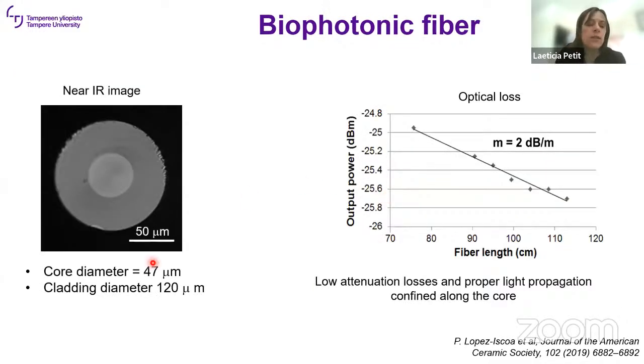So here's the near infrared image of the fiber. So the core diameter is 47 micron and the total diameter was 120 micron. And we got 2 dB per meter losses. So the low attenuation loss and the proper light propagation confirm that the light is confined along the core.